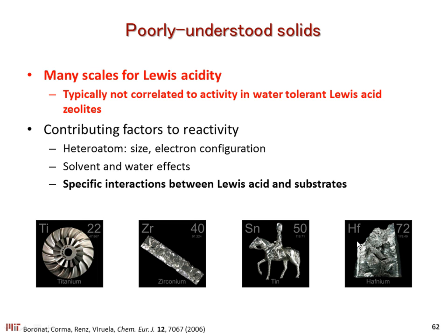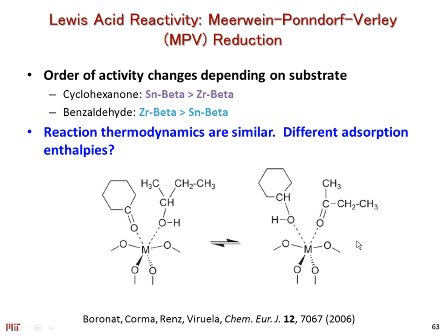We see very strong solvent effects. We see very strong heteroatom effects, and there has to be very specific interaction between this Lewis acid and the substrate. For example, in Corma's work, it has been seen that for these MPV steps, just changing from cyclohexanone reactant to benzaldehyde completely changes the activity if you use tin beta or zirconium beta under exactly identical conditions. So, there's a lot of questions as to what is happening there around the active site, and that is something that we want to probe a little bit more with NMR.